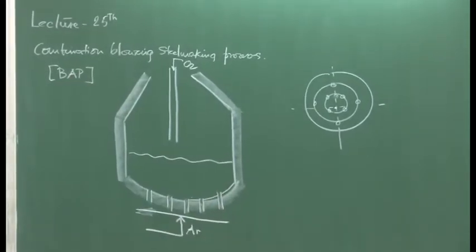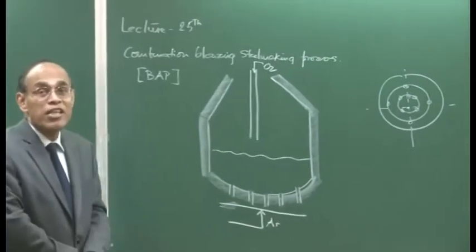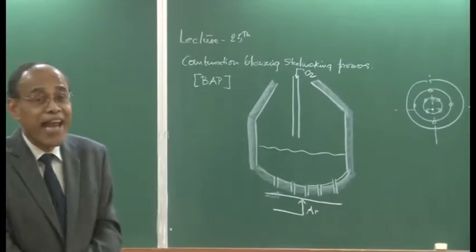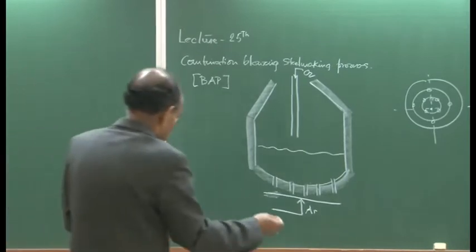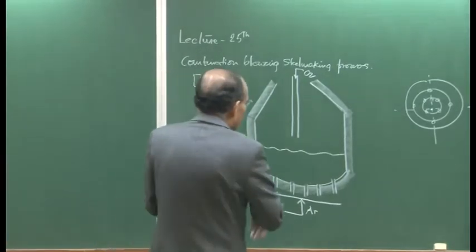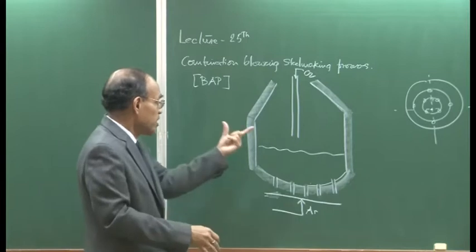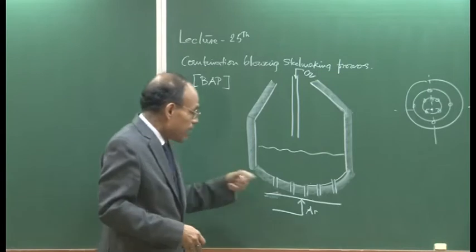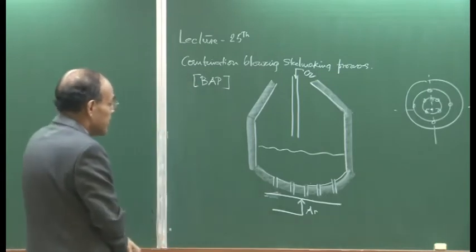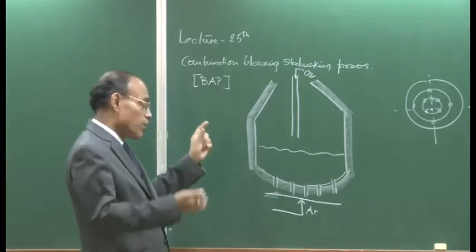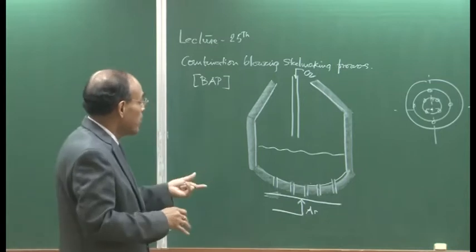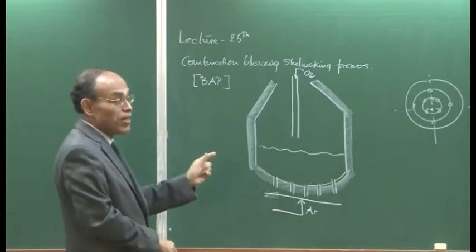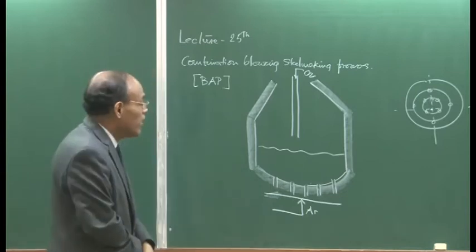The thermodynamics of dephosphorization, desulphurization, or decarburization need not be discussed; only their rate is going to be different depending on the kinetics of the process, because the vessel geometry is identical. The stirring pattern and stirring intensity are different depending on whether you have a top blowing, combination blowing, or a bottom blowing steelmaking process. We would expect that the kinetics are going to be a little bit different.